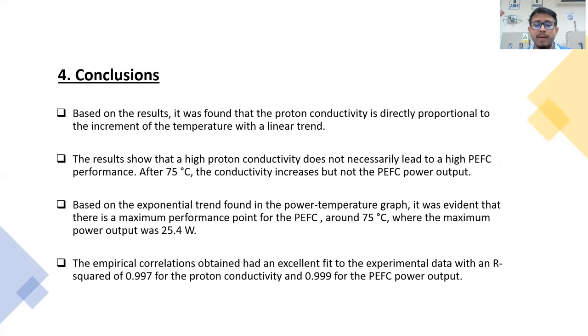Conclusions. Based on the results, it was found that the proton conductivity is directly proportional to the increment of the temperature, with a linear trend. The results show that a high proton conductivity doesn't necessarily mean a high PEFC performance.